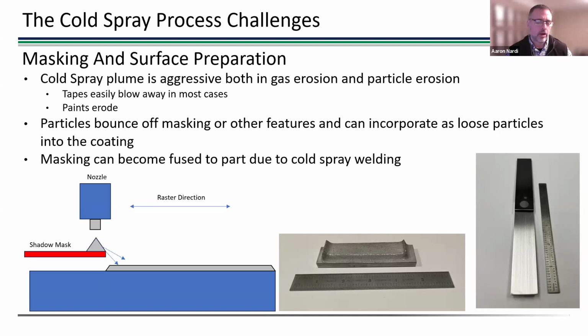So trying to manage where you have your mask, how you turn around on your mask, and so forth is really important. Now in the middle image there, you see just a standard raster pattern aluminum. And at either end of the aluminum deposit, you see this ski jump that occurs where the robot turns around. Anybody who's done cold spray has seen this. It's very common. Understanding that and understanding the defects that are going to occur in that turnaround area, as well as adjacent to this turnaround area, because of the same issue you had with your masking, you're going to get deflections off of that little ski jump, and those deflections are going to accumulate somewhere else in the material.